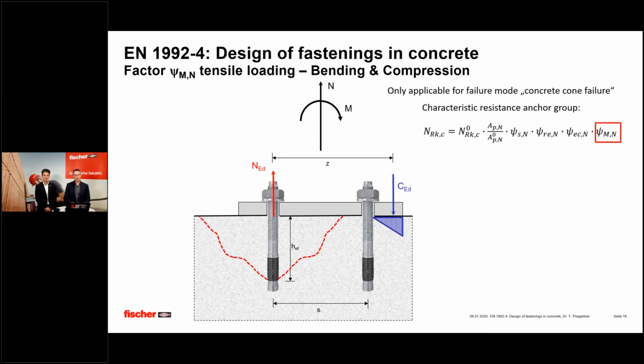With the bending moment, you get a compression zone under your fixture, and the bending moment in combination with a tension load causes the left anchor to be pulled, and on the right side you have this compression zone. In this case, the ratio between tension load in the anchor and compression load in the compression zone is relatively small, and the inner lever arm, this value z, is very big, and in that case you cannot apply any additional increasing factor. So psi M,N stays 1. This is also the case for applications close to edges.